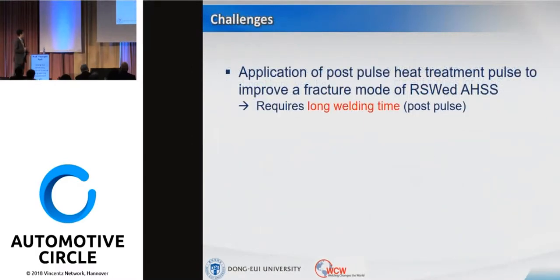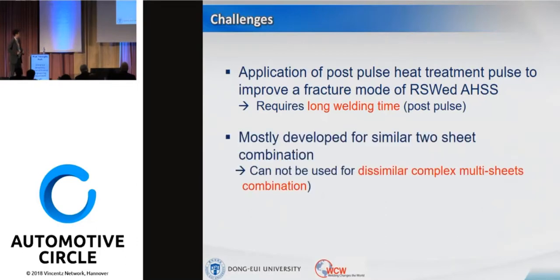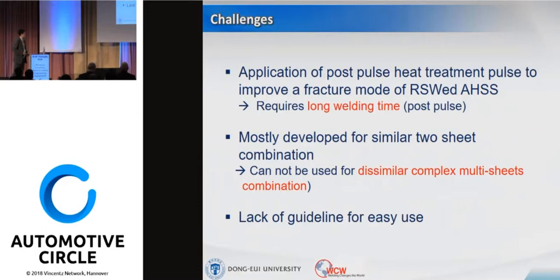But I looked into some of the challenges we have now. Application of a post-pulse heat treatment pulse to improve the fracture mode of resistance spot welded advanced high-strength steel requires a very long welding time, sometimes more than 40 to 50 cycles. Secondly, these are mostly developed for similar two-sheet combinations, so they cannot be used for dissimilar complex multi-sheet combinations like 3T or 4T stack-ups. And there is also a lack of guidelines for easy use.